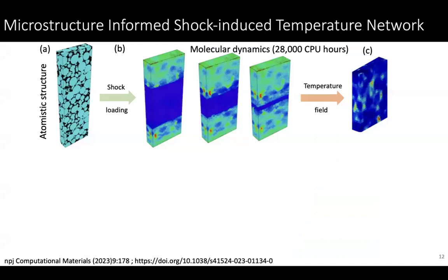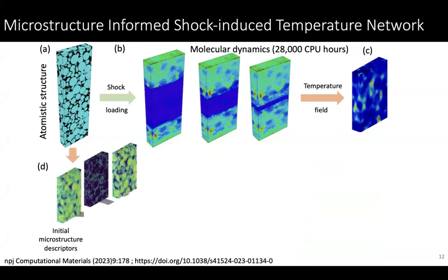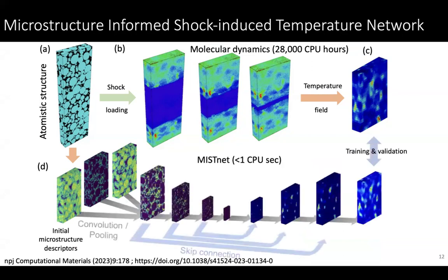And so we took our simulations, we ran a bunch of these simulations, different microstructures, and we use a technique called convolutional deep neural networks to try to learn the mapping between the initial microstructure, 3D microstructure, 3D image to the final 3D temperature field, okay? And I'm not going to go into the details, so I can cover a lot of cases, a lot of examples, and you can ask me.